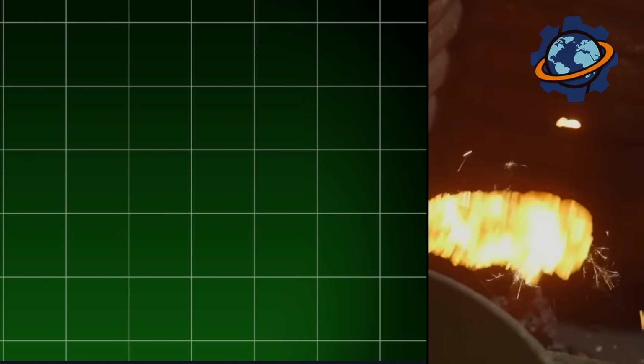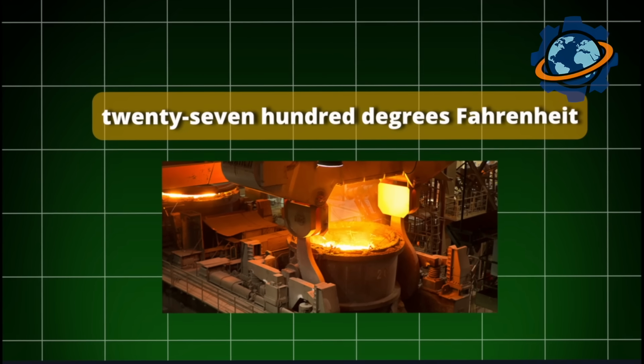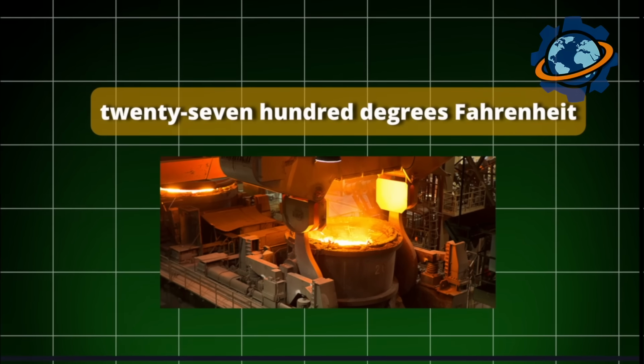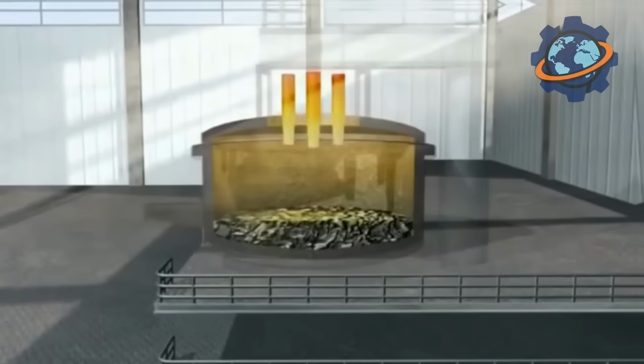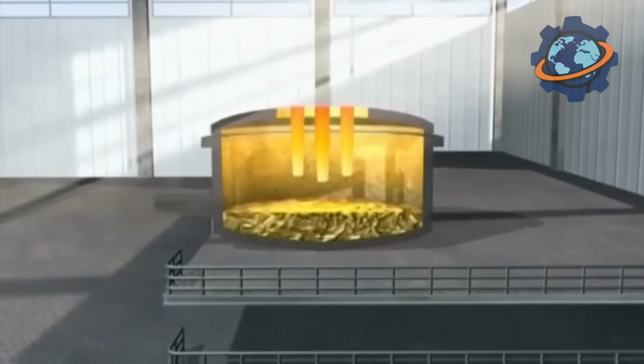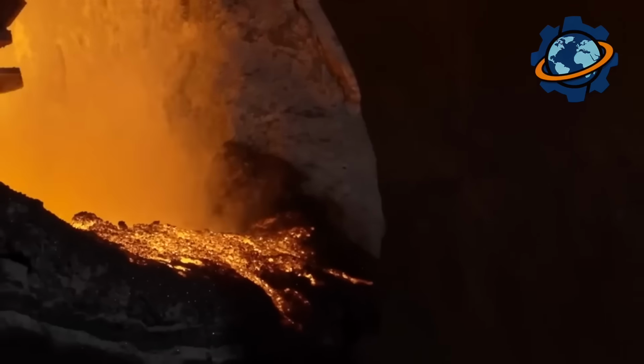At the furnace bottom, molten pig iron accumulates, an iron alloy with 4% carbon. Pig iron temperature at the furnace bottom is 2,700 degrees Fahrenheit. It glows blindingly white with an orange tint. Pig iron is denser than slag, so it stays at the bottom. Slag, molten impurities and fluxes, floats on top. Every 4 hours, they open the tap hole, an opening in the furnace's sidewall.